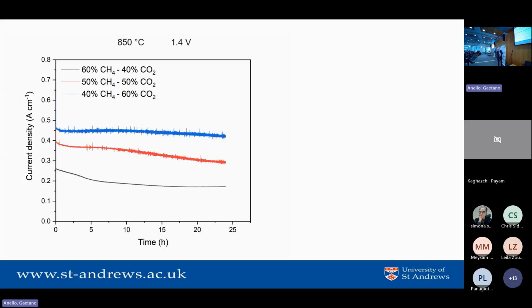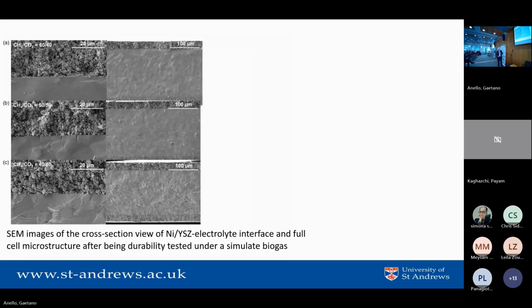In terms of conversion, you can see that the 60% methane, 40% CO2 has the lowest current and has this degradation. Whereas the other two compositions are richer in CO2, so less useful as a fuel, but are more stable.